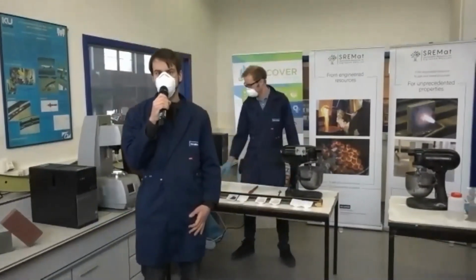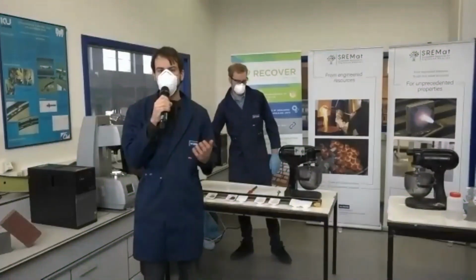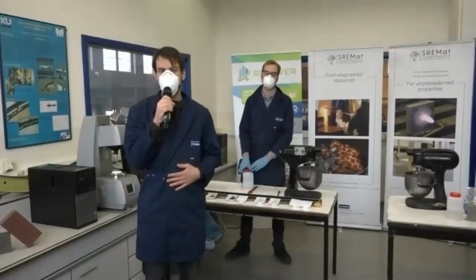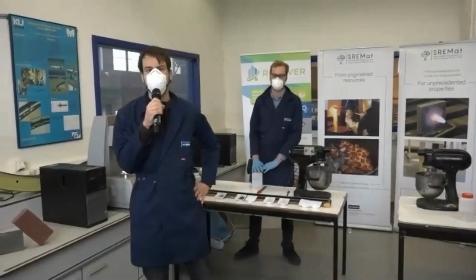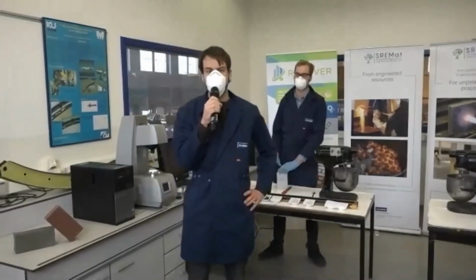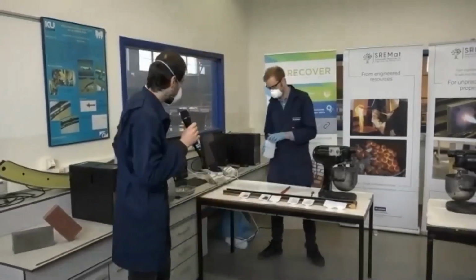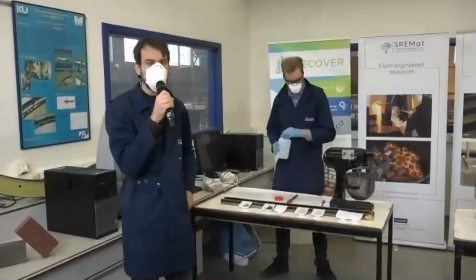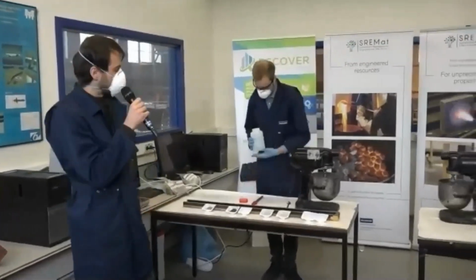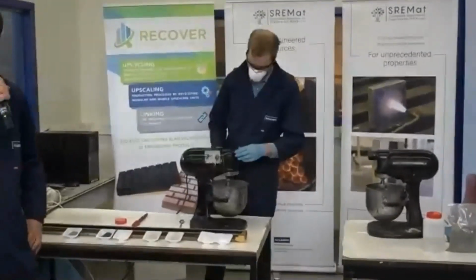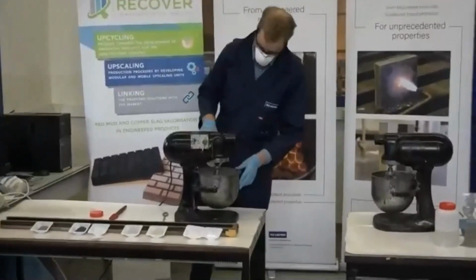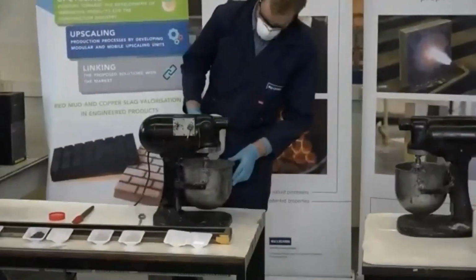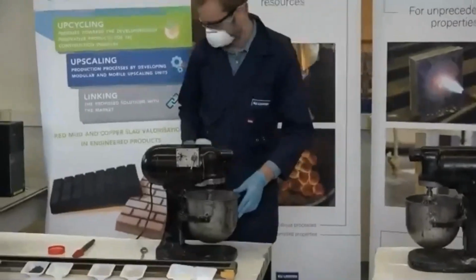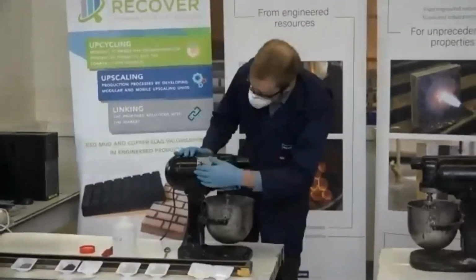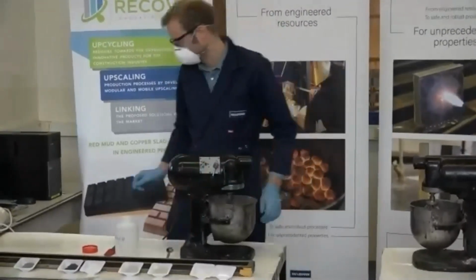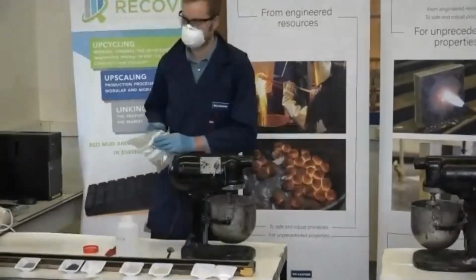What I also want to mention is that this work is based on a patent that was filed from KU Leuven, and the work was initiated by Lucas and by Yannis. So Michiel will now start to add an alkaline activator. We still need an alkaline activator in these hybrid binders, but the molarity of the activator is much lower compared to an inorganic polymer system. So in this case, he adds 1 molar sodium hydroxide.